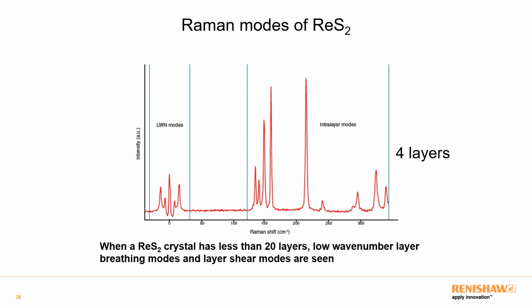This is a typical spectrum of rhenium disulfide collected with an inVia Raman system. You can see there are a number of different features here. So in this range and going upwards, we have a number of Raman modes. As I mentioned, it's very anisotropic, so you have a large number of modes. However, if we look down here, very close to the laser line, we have these low wavenumber modes. And these low wavenumber modes are a result of the individual layers of the rhenium disulfide crystal moving past one another. So you can either have them moving in plane or in shear. And these are responsible for these very low energy modes.